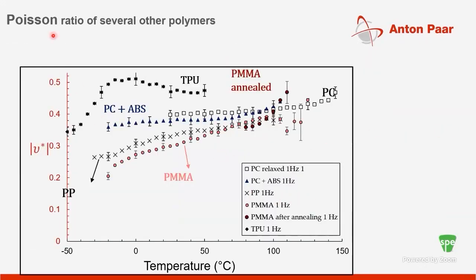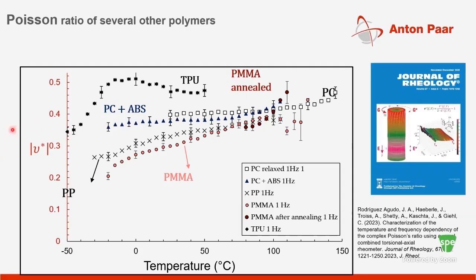We applied this combined axial-torsional formalism to multiple different polymer types, like amorphous and semi-crystalline thermoplastic materials, and characterized the Poisson ratio as a function of temperature. More details are in this paper, published in 2023 in the Journal of Rheology, which also ended up as a cover article on the front page of JOR. You can see Poisson ratio is not really a constant, but really changes with temperature.